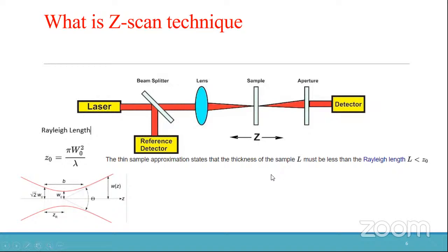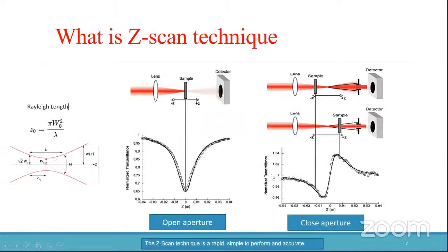So Z-scan is divided in two parts. One is open aperture and the other one is the close aperture. In open aperture, we scan the whole beam after transmission through the sample, while the sample moves from minus Z to plus Z, and this scan is used to calculate the nonlinear absorption coefficient. As you can see here, the profile of the absorption.